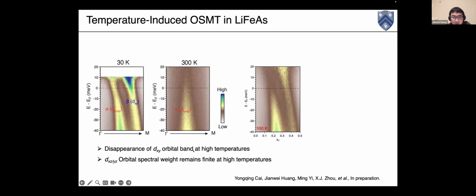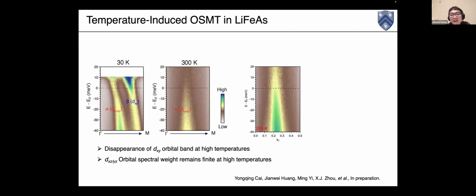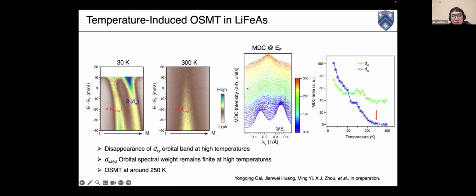This seems to suggest that lithium iron arsenide also goes into a Mott phase at sufficiently high temperature. So we can extract this band from the momentum distribution curves at different temperatures. The blue line is the low temperature at 30 Kelvin, and the yellow line is the high temperature. From these MDCs, you can also find that the XZ/YZ band still exists, but the XY orbital completely disappears.